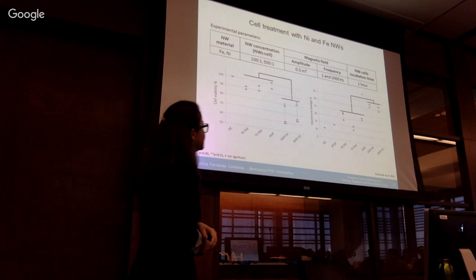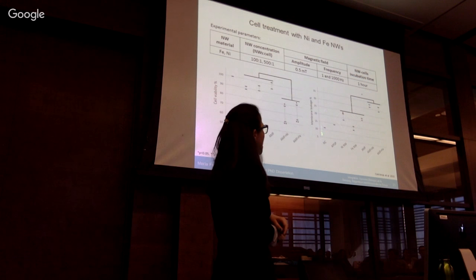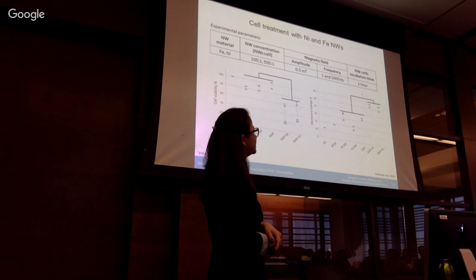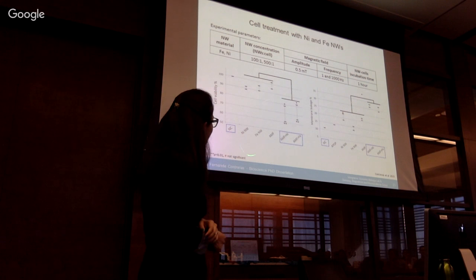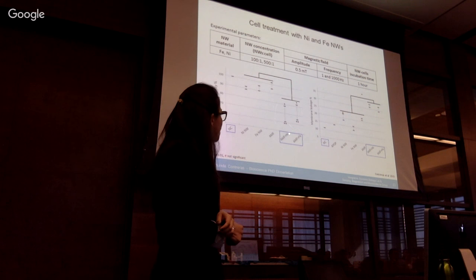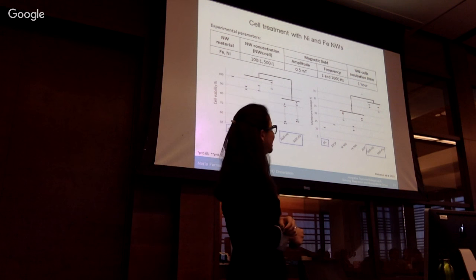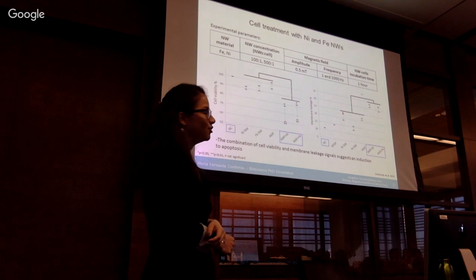This is not observed for the membrane leakage. The controls did exert some moderate leakage. However, the treatment increased it a bit more, making the cells leak more. If we focus on the combination of these two signals, some reduction of the cell viability and a moderate increase of cell membrane leakage, the two together suggest an apoptotic induction of the